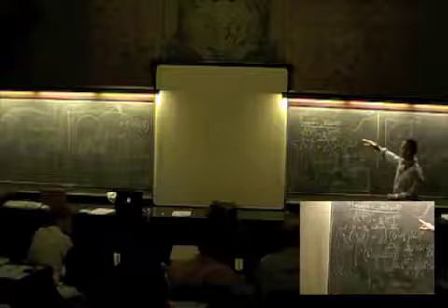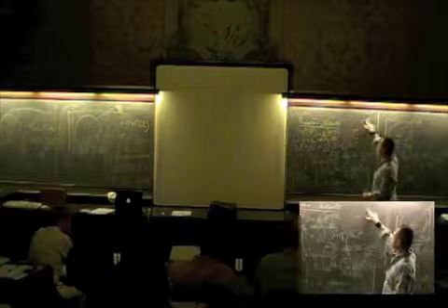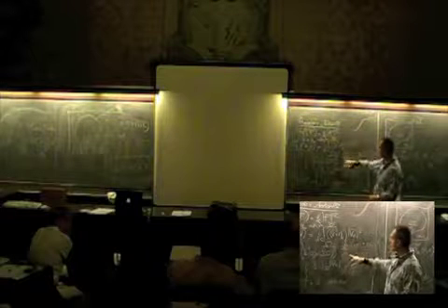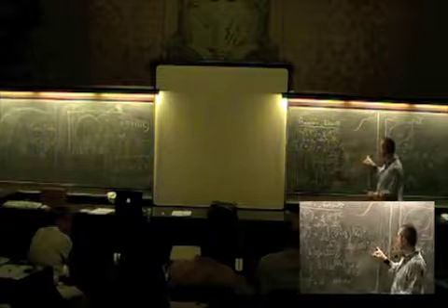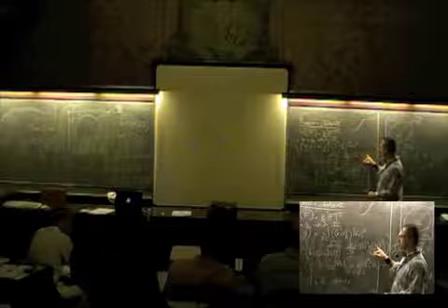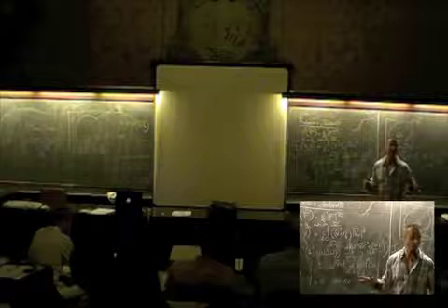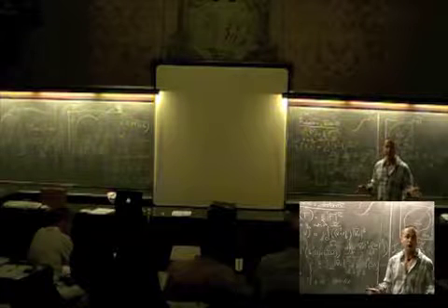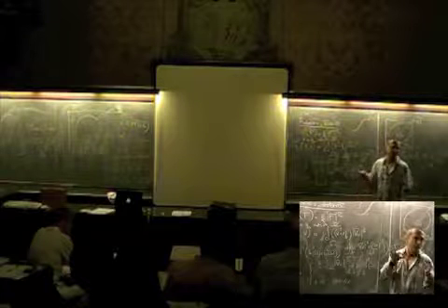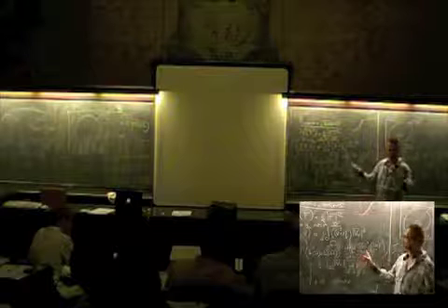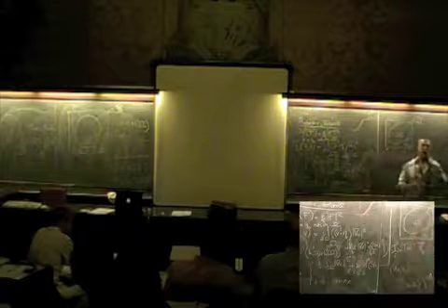Yeah, and then you've minimized at a given step. So what I'll show you is, let's say, the set of points where V epsilon is less than 10 to the minus 2. And I'll say that's my crack. Why 10 to the minus 2? So that I get something which is fairly thin. If you want, you could do it at 10 to the minus 4 or whatever.